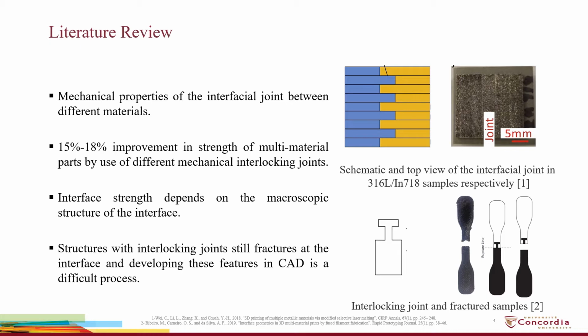In one of the previous research studies, Lin Li analyzed SLS 3D printed samples and found that mechanical properties of an interlocking interfacial joint between stainless steel and nickel alloy are in the range of the materials forming the joint, and the properties vary with the composition of the joint.